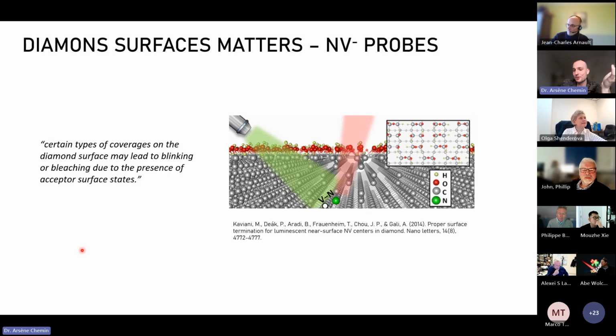So I talked a lot about electrochemistry, but I think many of you might actually be interested in quantum sensing and NV centers. As it has been said in that paper from 2014, certain types of coverage on diamond surfaces may lead to blinking and bleaching due to the presence of acceptor surface states. And indeed, we understood since then that depending on the surface termination, hydrogen, oxygen, or nitrogen, as I will explain later, we can have many different charge trapping happening and blinking of the surface states.